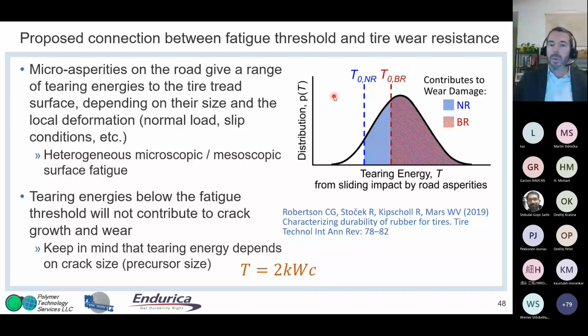If you have a distribution of tearing energies that are happening, again, from that very heterogeneous situation at the surface where road asperities are sliding past the surface of the road, and there's some distribution of these, anything below the fatigue threshold, which is here for natural rubber and which is here for butadiene rubber, will not contribute to damage. So if you have a higher fatigue threshold, then some of those events that are happening at the surface won't cause crack growth. And so based on this, we can understand that the higher fatigue threshold for butadiene rubber may be one of the reasons why it has better wear resistance than natural rubber.